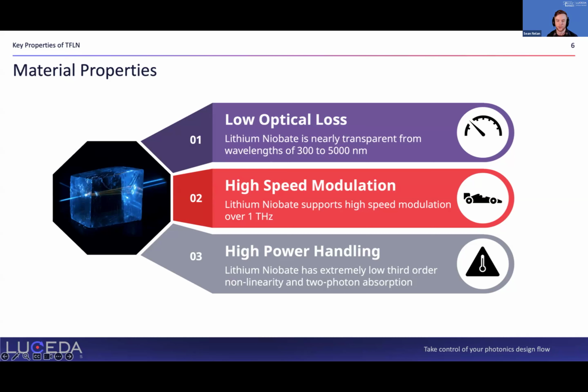High-speed modulation, we'll talk about this in just a bit, but lithium niobate uses a modulation scheme that's different from silicon plasma dispersion or indium phosphide or III-V based modulation. So this promotes high-speed operation and low-power operation. Now, a big requirement in quantum photonics as of late has been high power handling. Lithium niobate can support extremely high power density in its waveguides without any sort of third-order effects or crystal damage that might blow up your chip.